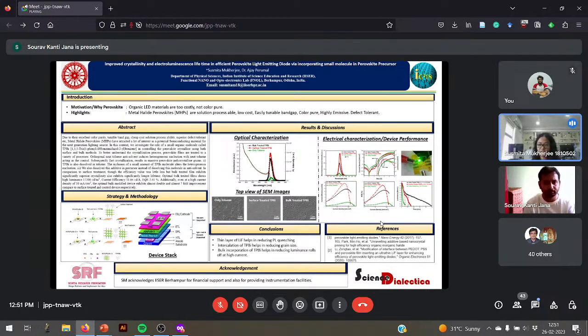In the optical characterization, I saw that if I dope TPBI in surface and bulk, in the surface treatment, the perovskite photoluminescence is enhanced and the grains become smaller. So my radiative recombination is enhancing. More bright luminous photoluminescence turns into brighter LEDs. In the electrical characterization part, you can see device performance. I went to the device then. A basic PN junction diode. I use PEDOT:PSS as hole transport layer, perovskite as my emission layer, and aluminium is my cathode. I made the devices, and I observed that it gave very high luminescence, more than 17,000 candela. And the main attractive thing about these LEDs is that they are much more stable at high current density.